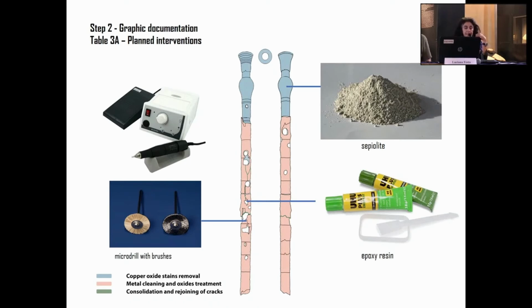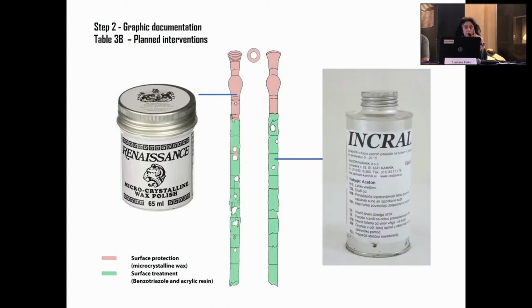Then to connect the cracks and also to connect the detached parts, it's possible to use epoxy resin. The epoxy resin is very stable. In normal conditions, it doesn't change in color and doesn't lose its properties of joining the detached parts. And so this is a part of the project of intervention. The last part of the intervention is the protection of the surface. We have to protect it against new degradation.